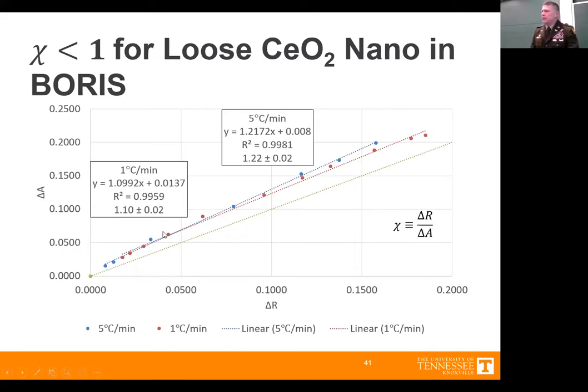So finally, the results, kind of what I was after. What I noticed in my work was that no matter what I did, my chi was always less than 1. For loose powder sintering specifically, there was nothing I could find that would cause the shrinkage in the radial direction to ever be as much as the shrinkage in the axial direction. It always shrank more in the axial direction than the radial direction.